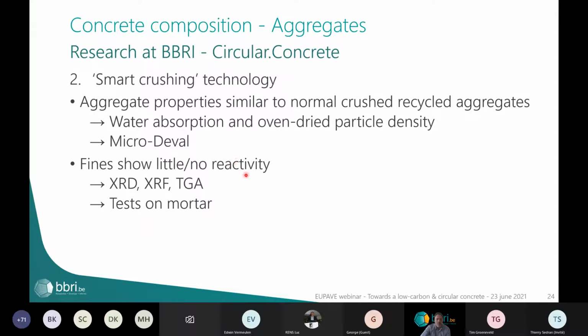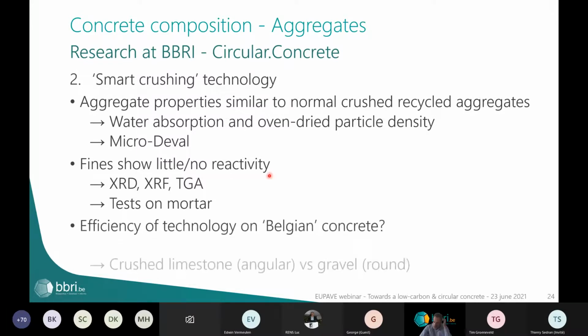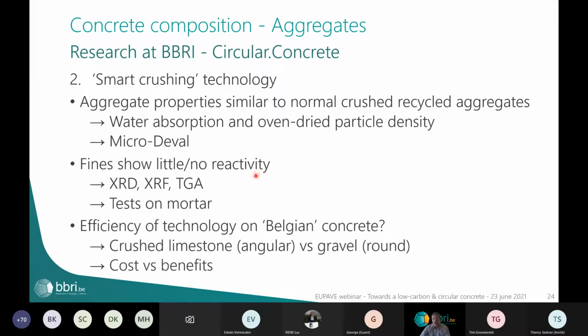We also looked at the fines, the powder fraction that we received. We looked at the reactivity as such, without any heat treatment or such. We just used it like this in mortar, and we did not see any contribution to the strength development of these fines. And we also looked at it under different analyses, XRD, XRF, TGA analysis, and it all concluded that in fact there is little to no reactivity left in those fines. So perhaps it has to do with the Belgian concrete. We use a lot of crushed limestone in our concrete in Belgium, whereas in the Netherlands a lot of rounded gravel is used in concrete.